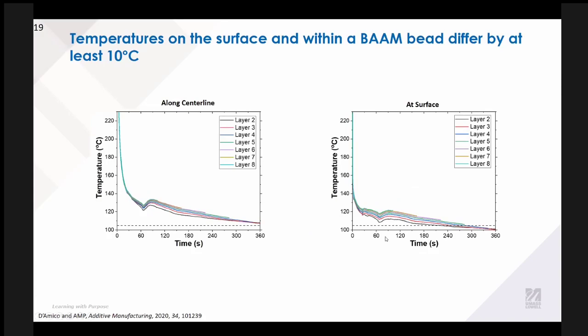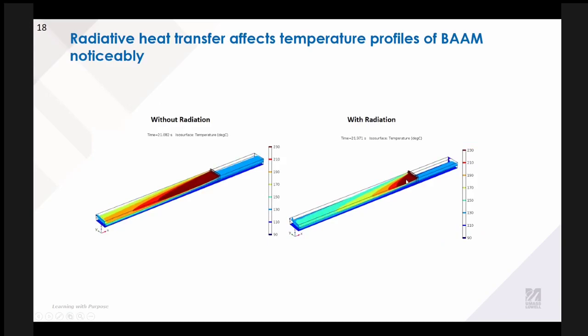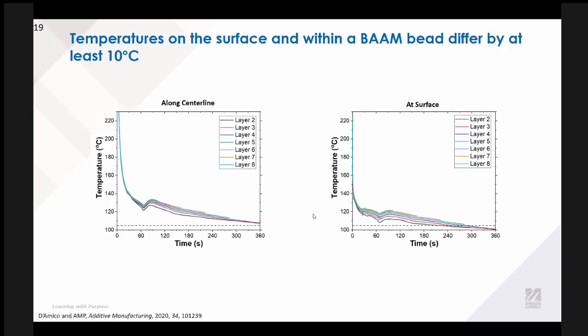All right, one thing that you probably noticed in these animations, I can jump back, is that there is a fairly large temperature gradient between the center. So this is a cross section of our print. So between the center of the bead and then the surface, which would be exposed to air, we see that the temperature difference can be at least 10 degrees Celsius, which is a pretty large temperature difference across a relatively small thickness, or I guess width would be the right dimension there. And so that can be a really big deal for warping and for residual thermal stress evolution. So this is something that we need to be considering in BAM that really wasn't a problem in FFF.